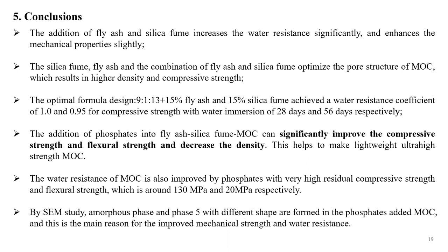The optimal formula design, molar ratio 9:1:13 plus 15% fly ash, 15% silica fume, achieve the water resistance coefficient of 1.0 and 0.95 for compressive strength with water immersion of 28 days and 56 days respectively.